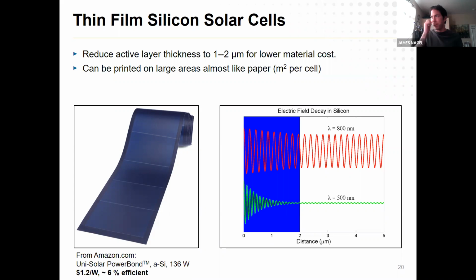And you see at 500 nanometers, it has this nice, strong attenuation, right? So over a distance of, say, 2 microns, I will absorb 95% of all the photons in the 500 nanometer spectrum here. But you just go up towards the red a little bit, 800 nanometers, and the difference is very dramatic. Now it needs 10 times as much thickness to get that same 95% absorption. And so I'm sacrificing a huge amount of my efficiency in those long wavelength photons. And remember, the band gap for silicon is way out at 1120 nanometers. So you're losing a sizable chunk of your spectrum by going thin.